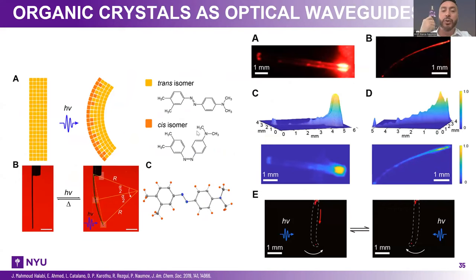So what this enables us is to use the UV light to control the shape of the crystal, and in fact to control the path of the light that passes through the crystal. So by using this kind of three-dimensional fluorescence map, we can actually see that we can have a spatial control over the light output from the crystal, by using two types of light, one passing through and one passing perpendicular to the crystal to control the crystal shape.